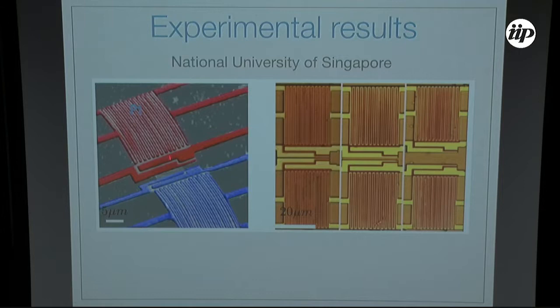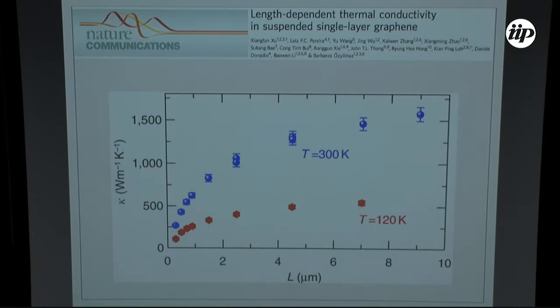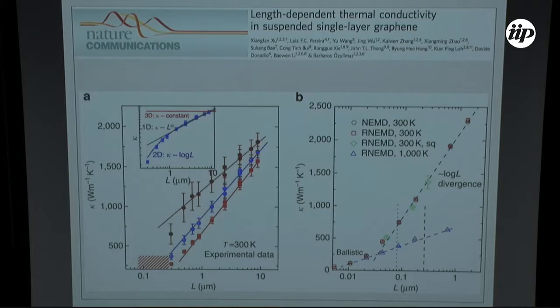These are measurements at 300K and 120K. The graphene patches are heated by passing a current through a platinum element, and this is connected to something with a colder temperature. They can do this for increasing separation, increasing the size of the graphene patch. They get this behavior, which on a log scale gives a logarithmic dependence — matching our simulations. In the experiment it's hard to determine the interface thermal resistance between the platinum and graphene, so they have different estimates, but in any case you get this logarithmic dependence in agreement with our simulations.